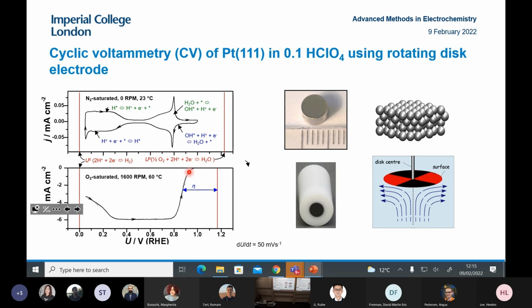And so you start to see oxygen reduction reaction activity increasing, and then it flattens out here. That's because it's transport limited. And the reason there's an inflection here is you start to make hydrogen peroxide. So usually you make hydrogen peroxide in this region because you're covering the surface with hydrogen. It becomes more difficult to dissociate the oxygen-oxygen bond in this region.